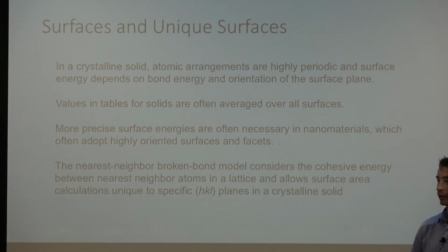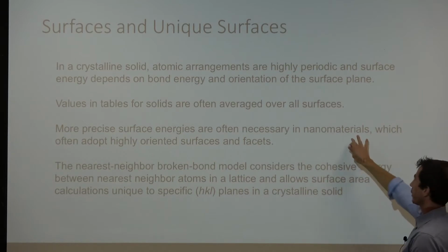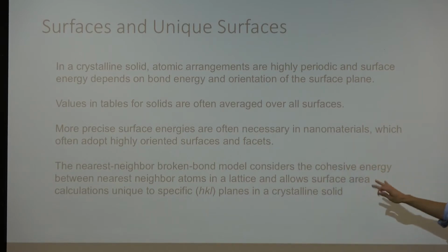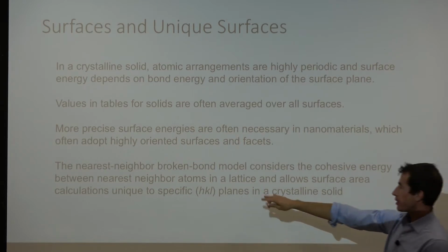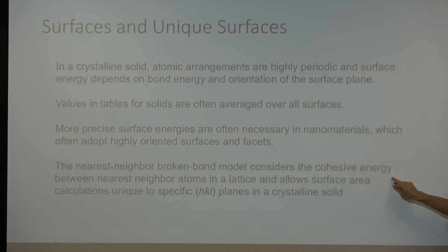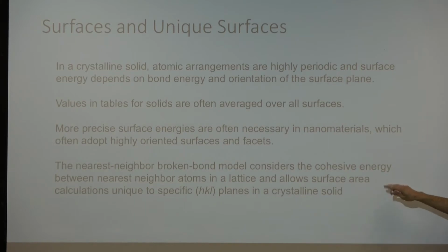It's not going to list it out for these different types of surfaces, but it makes sense that those do have different energies. More precise surface energies are often necessary in nanomaterials, which often adopt highly oriented surfaces and facets. Yes. The nearest neighbor broken bond model considers the cohesive energy between nearest atoms in a lattice and allows surface energy calculations unique to specific planes in a crystalline solid. Okay, so